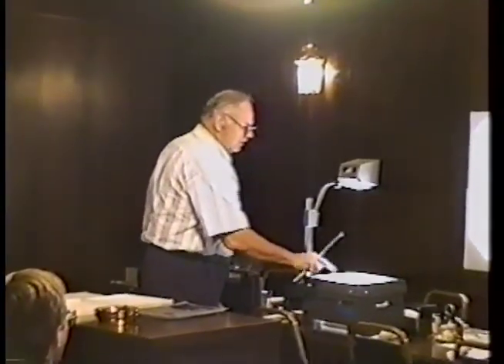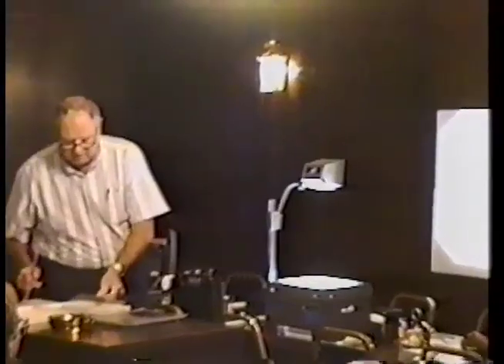Some other technical factors which explain why it is such a good product for rebuilding is that it does have a very high melting point. 1900 degrees centigrade for chrome compared to 1540 in cast iron. But more important is the fact that it does have a rate of expansion equal to, or nearly equal to, that of cast iron.